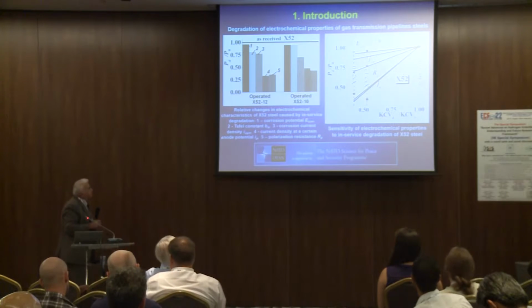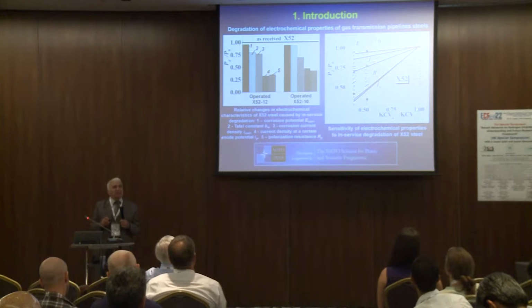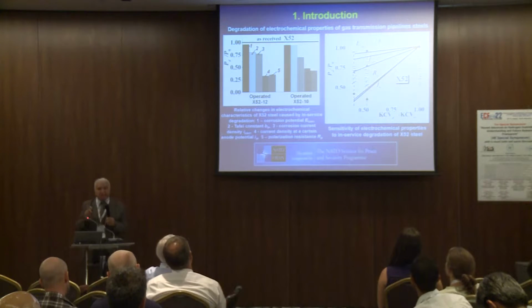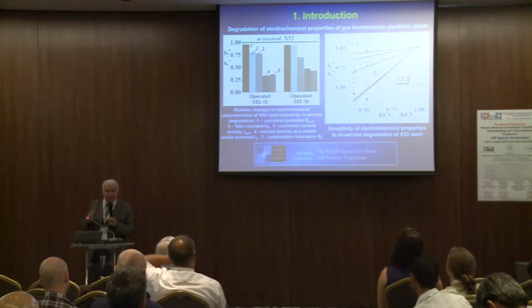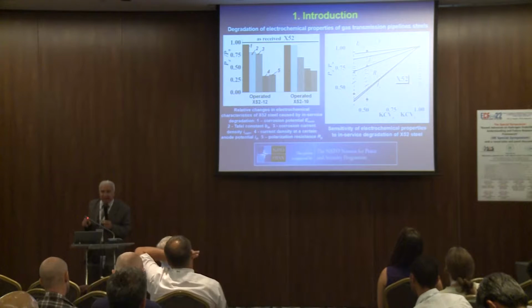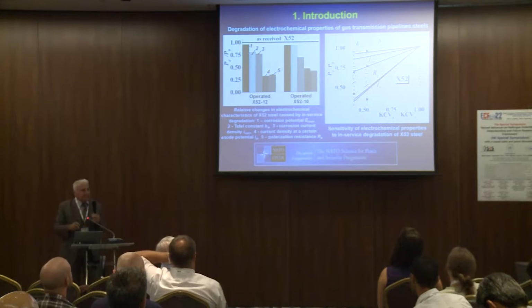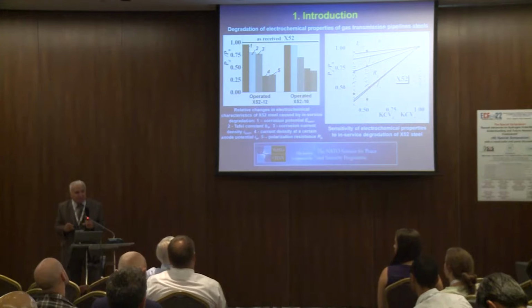And in previous work, we proposed to use electrochemical measurement for an evaluation of mechanical properties of in-service degraded steels, because some electrochemical properties are sensitive to aging of materials.